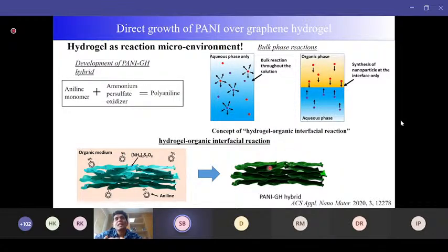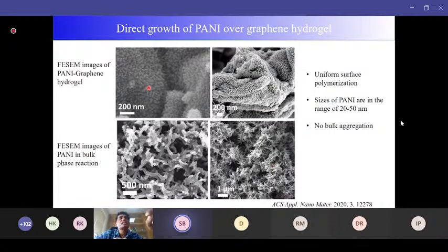This is a schematic image where you can see that each individual graphene surface is covered with very tiny polyaniline structures. And here is the FESEM image. The background is the graphene, over which you can see spikes in the range of 20 to 50 nanometers. So we can downsize the polyaniline. And as you can see, this is another sample where we can also control the lateral dimension of these structures, and they grow over the graphene. There is no bulk phase.